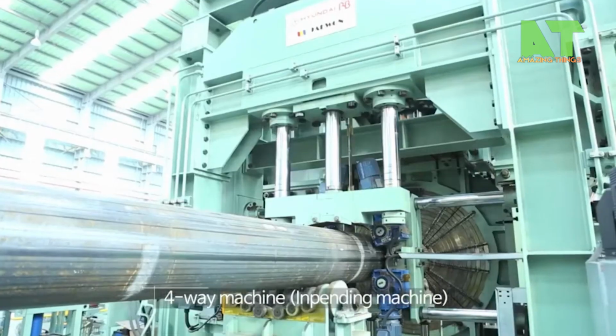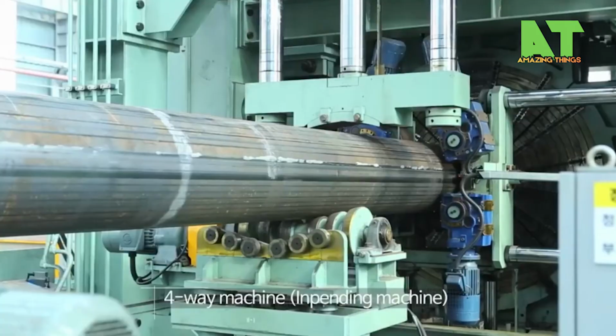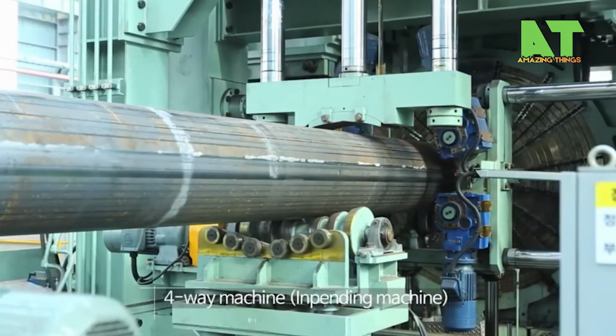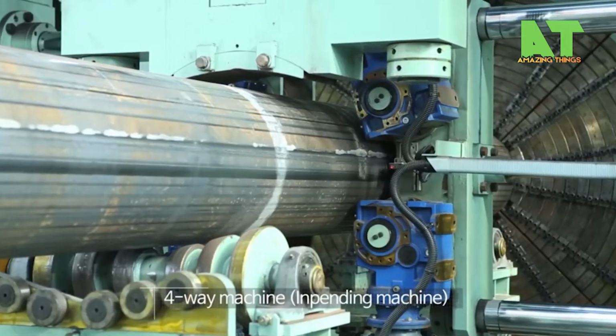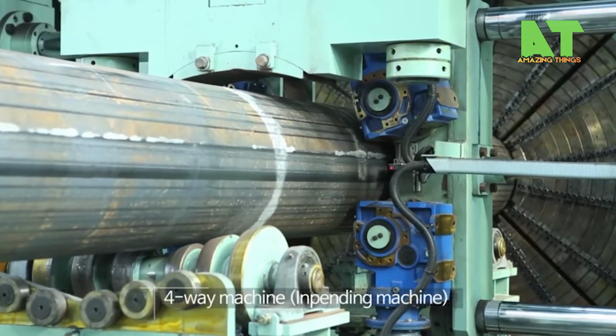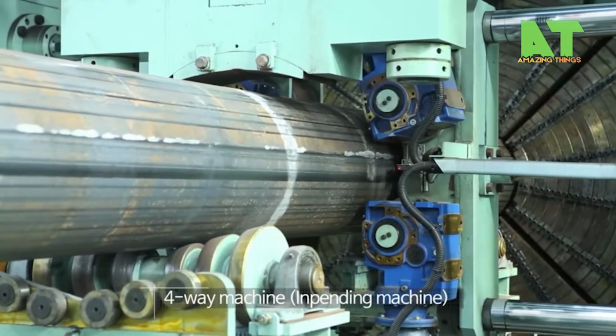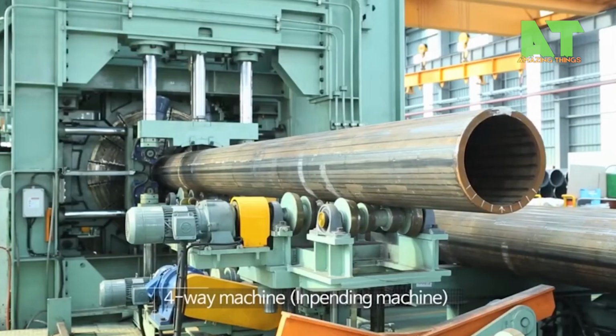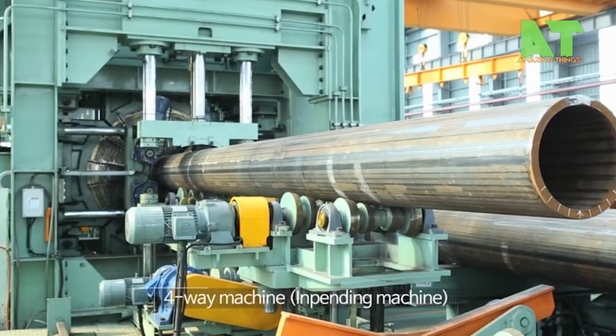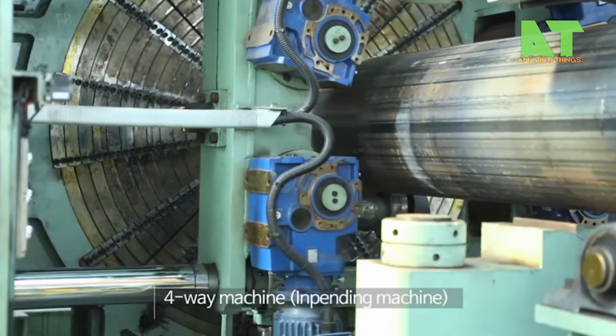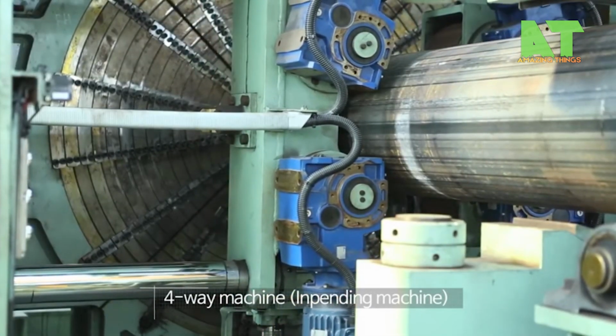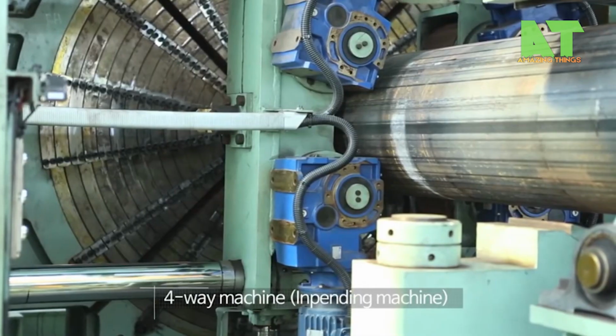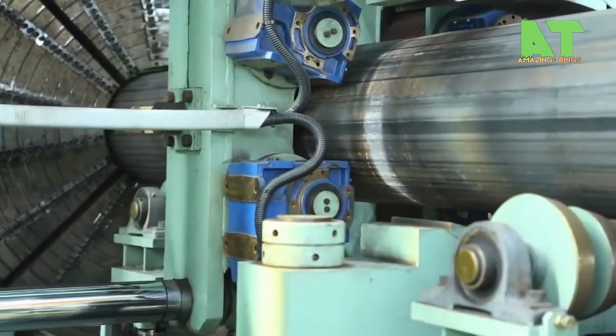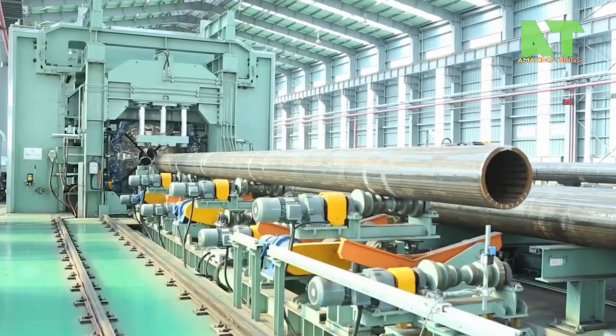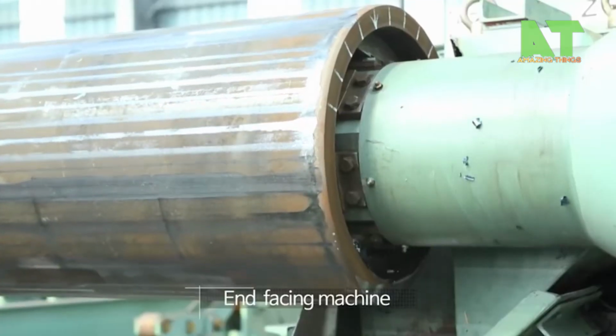Every single weld seam is inspected using ultrasonic testing and X-ray examination. These tests can detect the tiniest internal flaw, a microcrack, a void, a lamination, without ever cutting the pipe open. Only pipes that pass every inspection move forward. Final steps include hydrostatic pressure testing, end beveling, anti-corrosion coating, and dimensional verification before each pipe earns its quality certification and heads out to customers around the world.